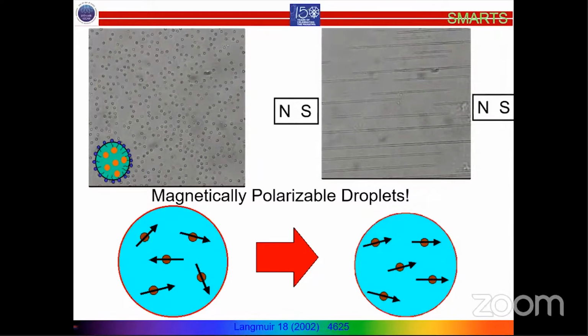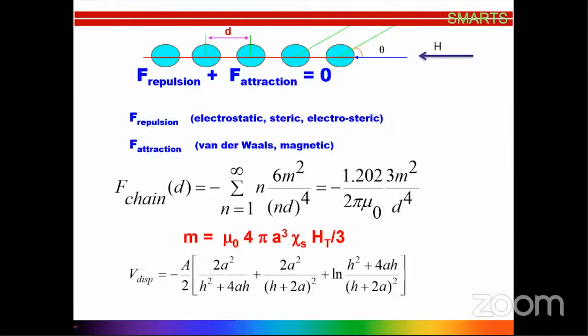If you are able to control the interparticle spacing, it is very easy to measure the force as a function of distance in this system, because when it forms a one-dimensional array, the net force is balanced. What is the net force I'm talking about? The forces due to repulsion and the forces due to attraction. Forces due to repulsion depend on the kind of stabilizing moieties that you use. It can be electrostatic, steric, or electrostatic-steric, depending upon the surfactant molecule or polymer surfactant that you use. And the attractive contribution at very small interparticle distance originates from the van der Waals forces.